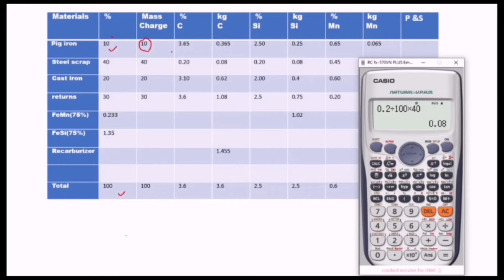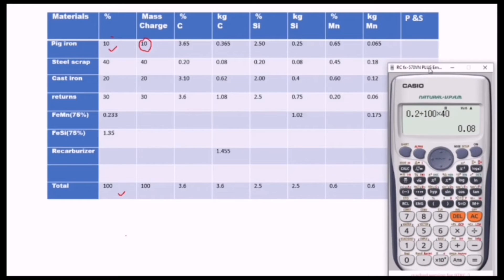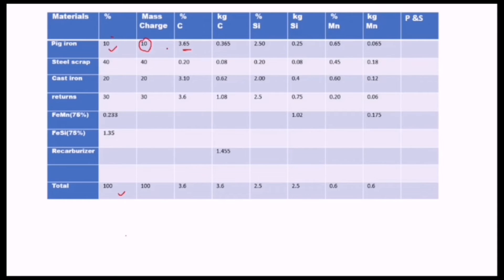For silicon, it forms 2.50% of the pig iron. With the pig iron, the mass charge is 10. So you are going to find 2.5 over 100 times 10, which gives you 0.25. You apply the same for the manganese. With the manganese, we have 0.65% of the pig iron. Since the mass charge of the pig iron is 10, it will be 0.65 over 100 times 10, which gives you 0.065.